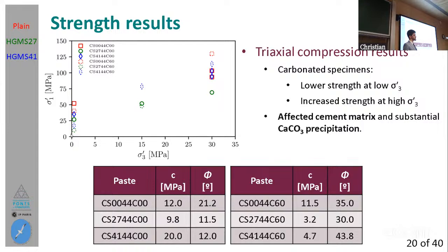With this data, we're able to obtain these strength parameters that we will then use in the modeling part, which are the results of cohesion and friction angle for the non-carbonated samples in this table here and the carbonated samples in this table here. You will see that the cohesion here is relatively high and here is relatively low, and then the friction angle here is relatively low and here relatively high, which corresponds to the behaviors in there.